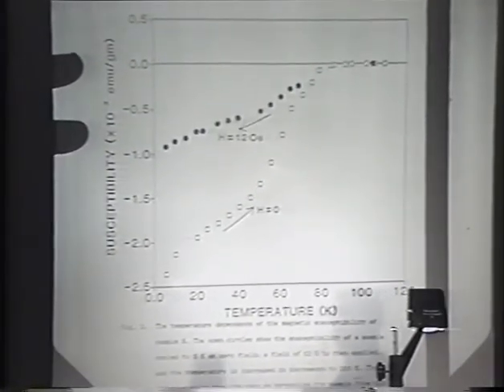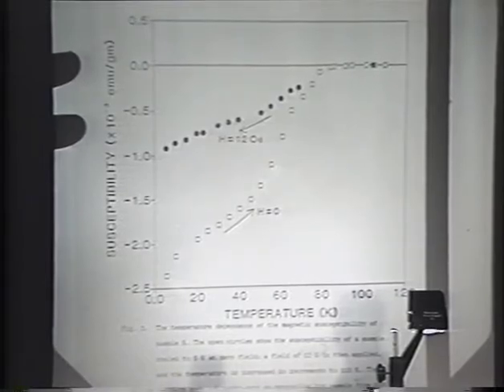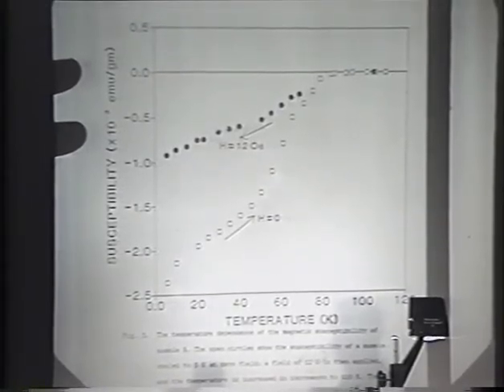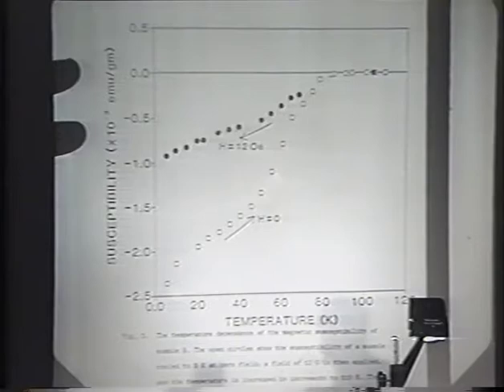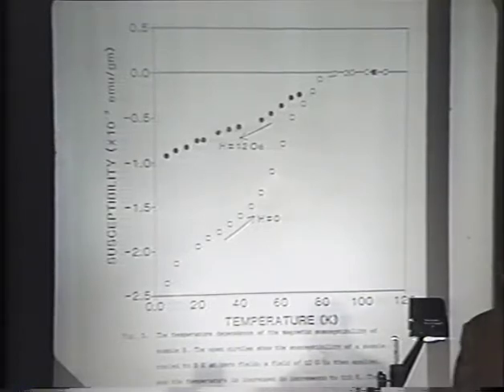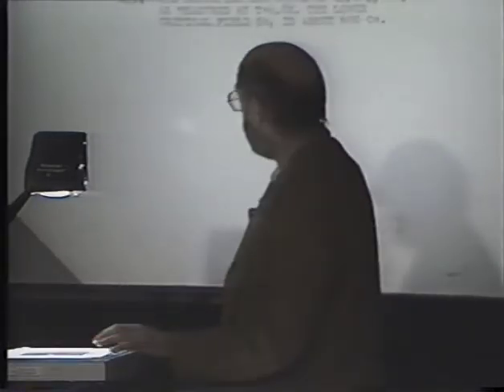This is the field cooling and zero field cooling. The lower sample is a sample cooled at zero field and then has 12 Gauss added to it. The upper one is one cooled through the transition at 12 Gauss. You've also seen these this evening. This is a magnetization curve from which we deduce an HC1 of about 600 Gauss, which is somewhat higher than an earlier number that I saw quoted tonight.